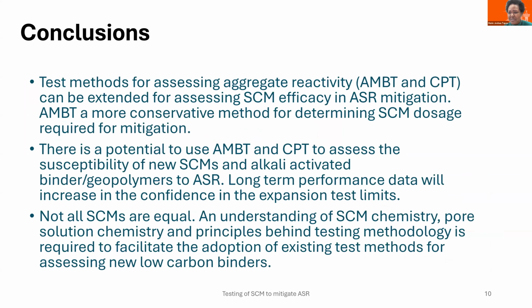So, conscious of the time, I have to go a little bit fast, but conclusions: the test methods for assessing aggregate reactivity can be extended for assessing SCM efficacy in ASR mitigation, based on the paper we've published 2 years ago, looking at long-term field data from the UK and from Canada, where our Australian standards and test limits are even more conservative and proved to be very well correlated to the long-term data. AMBT is a quicker method, 21 days, and even provides a better way to assess the required dosage, even a more conservative dosage for SCM mitigation.